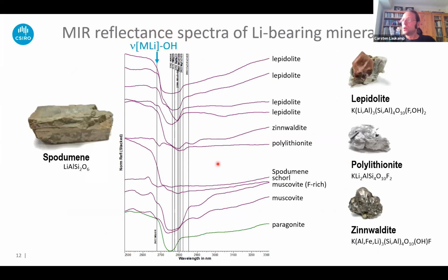Good, and some more spectra, this time from the midwave infrared. This is also a little bit of a frontier area because not many people have worked on the midwave infrared part of the spectrum. So it's all part of setting up the reference library of lithium-bearing minerals. I might just point out that there is, according to literature at least, a quite distinct absorption feature around 2,670 nanometers, which is assigned to lithium hydroxyl. We see that in some of the lithium-bearing minerals, but we also see this in a normal muscovite. And we are doing research on what's going on here.